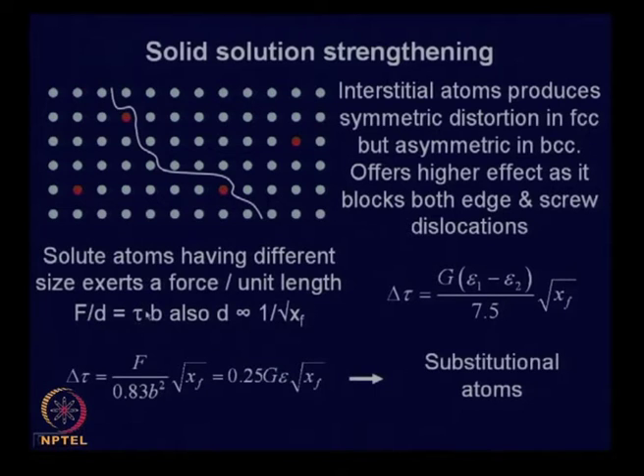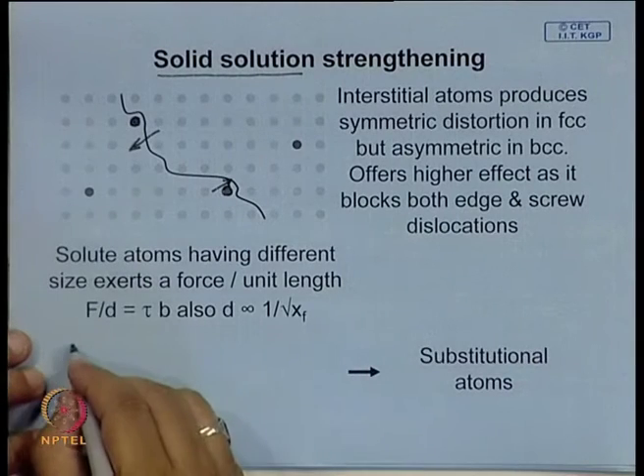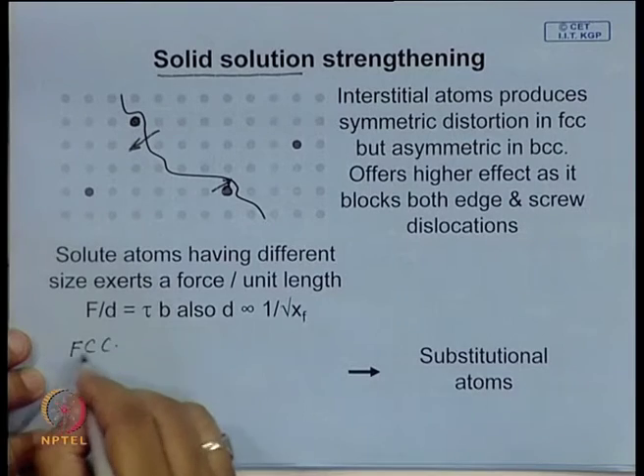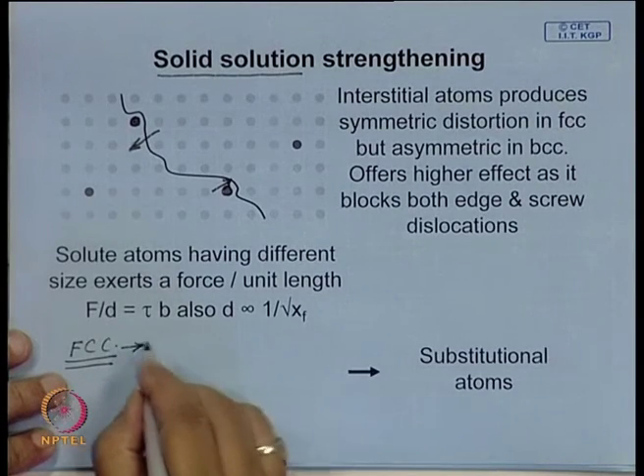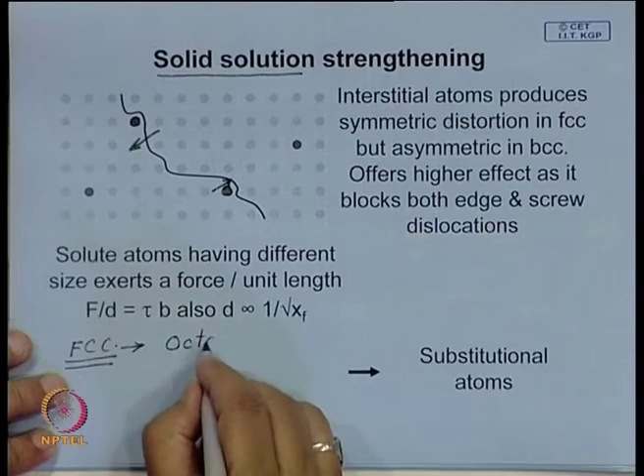you will find that increment in tau, the shear strength, will be proportional to square root of the solute contained, and this is the case where solute atom is a substitutional solute atom, and same thing can be extended to cases in the interstitial atom also. But interstitial atom, we know that in face centered cubic, in FCC, that means in austenite, carbon occupies, let us say, octahedral site,